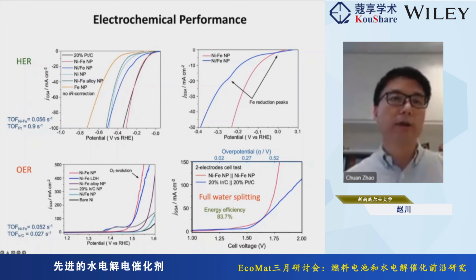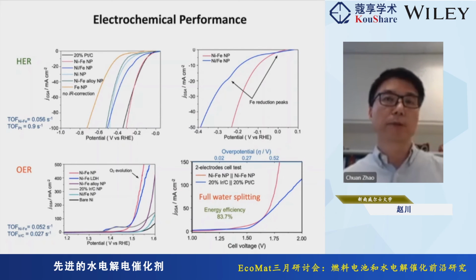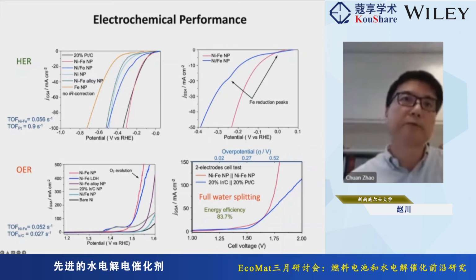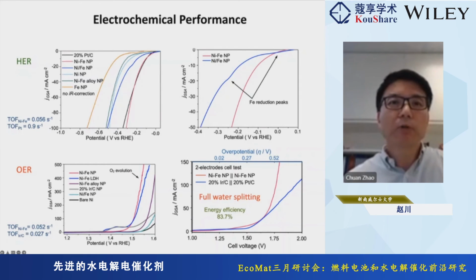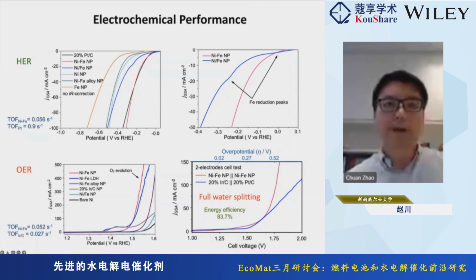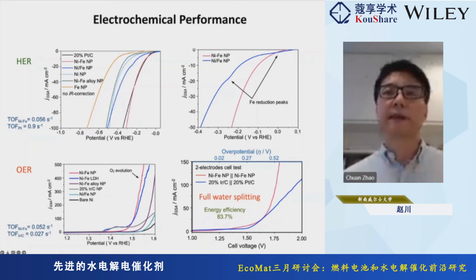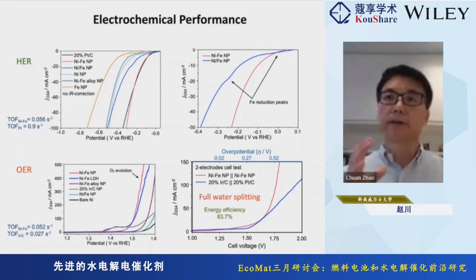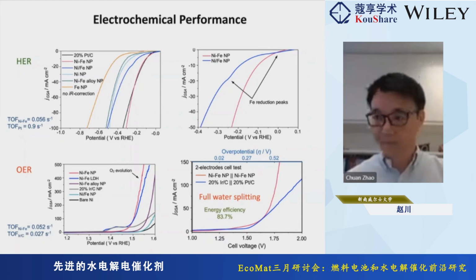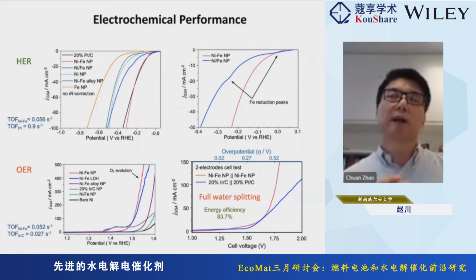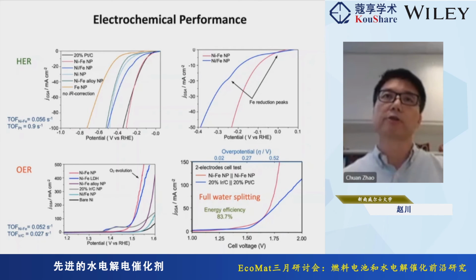With OER, the catalyst also has significant OER performance, which is expected for nickel and iron. I want to bring your attention to the pre-oxidation peak. With other catalysts like nickel iron LDH or other electrodes, you also see that pre-oxidation peak. But with our catalyst, that peak disappears. Again, that suggests the active site for the OER is not formed in situ. It's already there when the reaction starts. So we have active sites at the interface for both OER and HER.